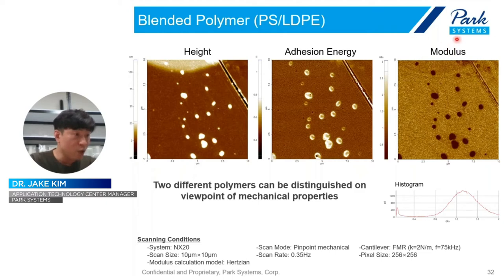And from this modulus image, we can check those numbers. This region is quite small, but here around 1.3 gigapascal, it is the PS. And here around 100 megapascal, this one is LDPE. Like this, we can do this quantitative mechanical property analysis using pinpoint mode.